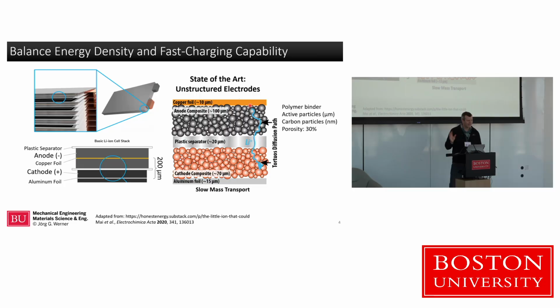Right? For different chemistry, that looks a little different. For lithium-ion batteries, it's really the lithium ions, hence the name, that shuttle back and forth between your anode and your cathode materials during charging and discharging, right? Now, these lithium ions in your standard batteries go through a liquid. That's called the electrolyte, and that liquid is imbibed in the porosity between these active materials here, which again are usually powders held together by some polymer. So that interstitial particle space is where your liquid goes, and that's where your lithium ions can diffuse or migrate around from one side to the other.